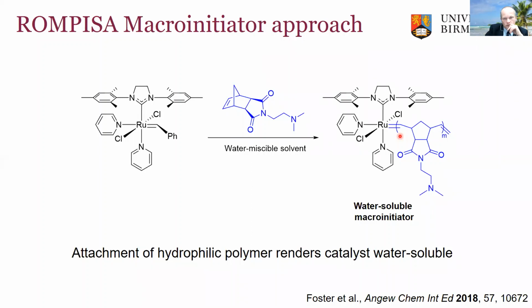in our PISA polymerizations. And one of the things we were quite interested in, and we became interested through a collaboration with Rob Mathers from UPenn, was thinking about the choice of monomer that you use for PISA. So as I said earlier, the concept of PISA is that if you're doing an aqueous PISA, you start with a water-soluble macro-CTA, and then you polymerize a monomer that is water-miscible. In the early stages of that second block formation, the very short DPs, that polymer is water-soluble, but then it undergoes a transition to become not water-soluble, transitioning from hydrophilic to hydrophobic, and that leads to the assembly.